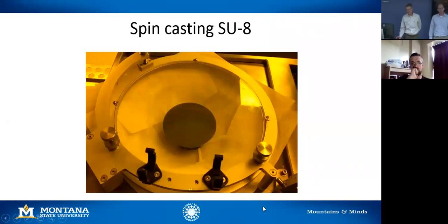Yeah. No, I assume that round thing is the wafer. That's the silicon wafer, 100 millimeter diameter wafer. That's our standard substrate size. And so the spinning is distributing the coating. Yeah. But I also heard you said you improved something. So I was trying to catch that. I wasn't sure if it was related to this. No, so the spin casting technique for these really viscous films is difficult to get good uniformity.